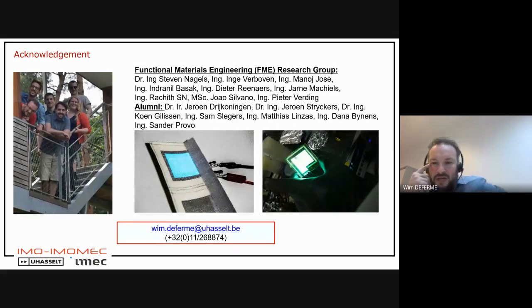And then, what is the mechanism of bonding between the substrate and the nanoparticle? Well, in principle, the thing we did is just depositing these nanoparticles on top of the substrate. So we do not really have a chemical bond. It depends on the application. If you look at the hybrid plasmonic, magnetic plasmonic nanoparticles, so the gold, there we really had linkers on the gold and on the substrate to make a chemical bond between those nanoparticles and the substrate.